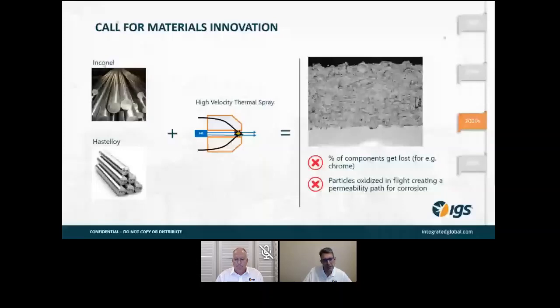So what we're looking at there, you can get an idea of how fine the microstructure is, which is typical of our high velocity alloy cladding process. But what you also see is a lot of dark gray in the material, and that dark gray is oxide. That's oxide that's formed during the flight of the particles towards the surface. And what we learned when we got into these more aggressive applications is that these oxide layers in the coating are paths where, in more aggressive corrosion environments, you can get permeation. So even though the system itself is dense, you can get permeation through these oxide layers.